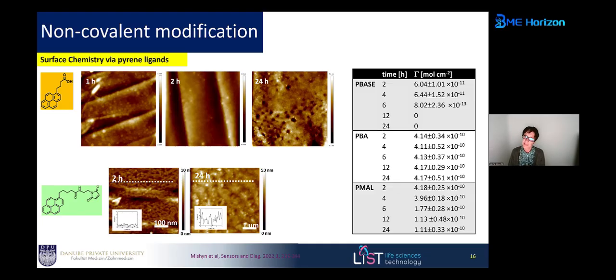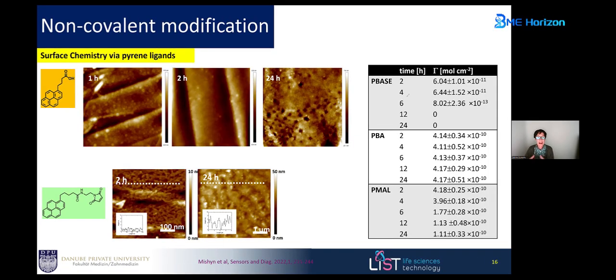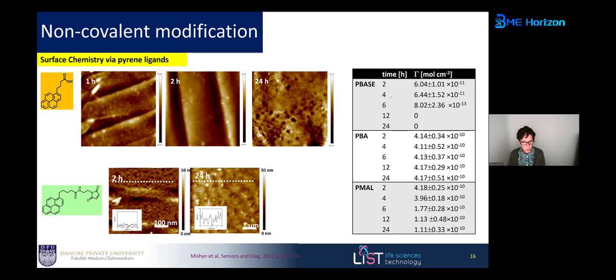So what that means actually, the PBASE, which is an ester, seems to be not very stable on the interface, that after 4-6 hours, it gets hydrolyzed, and then it will not allow further bioreceptors being integrated on the surface. So it might be not, even though widely used, the best approach to modify graphene. It can only be competitive to other chemistries if you really control the time to a very short time.